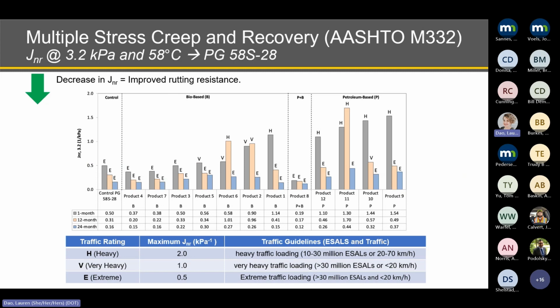We also evaluated the multiple stress creep recovery response of the binders. Here in the slides, you have data for the neat pavement surface with the binder PG58S-28. The same trend that was observed, considering the high temperature PG, can be captured here, where you can see that overall, for some of the treatments, we see a significant decrease in the stiffness of the binder. And as time progresses, that binder ages and the stiffness starts to increase. An important factor is that for some of the treatments, we have a change in the traffic rating after 1 month and 12 months of treatments being applied. But as we reach the 24 months, the traffic rating for the treated sections was exactly the same as the control.